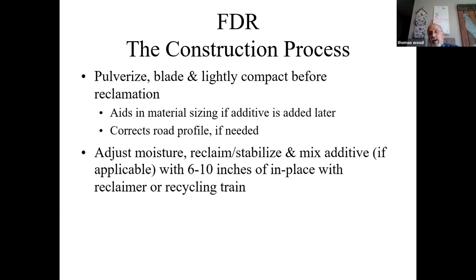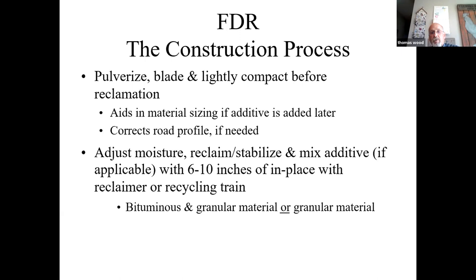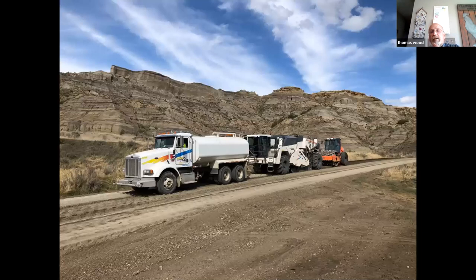Or we actually had at MnDOT an FDR project where the contractor came in with his reclaimers and ground it and pre-shaped it. And then he brought in his CIR train, just the milling machine and the processing plant. And he did the injection with that. And the reason why he did it is because trucks were short for hauling liquid, the emulsion. And this way he was able to pull a frac tank, and instead of having to make 4 passes to do a 24-foot lane, because you get overlap, he was able to do it in 2 12.5-foot passes. And it turned out really well. So just a bit of doing an injection there.